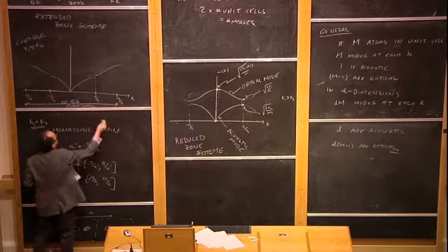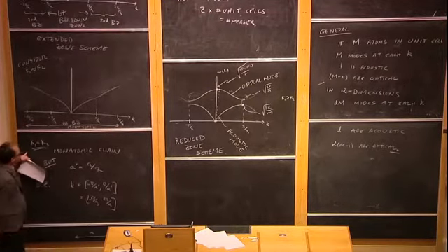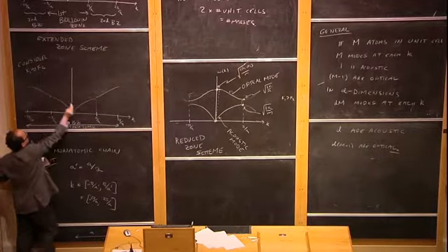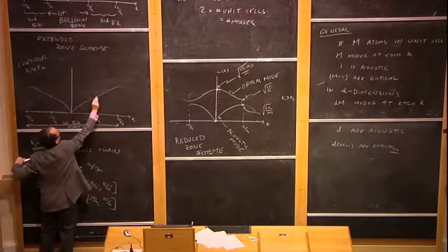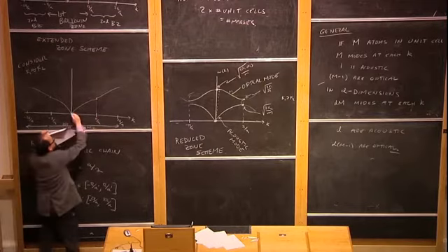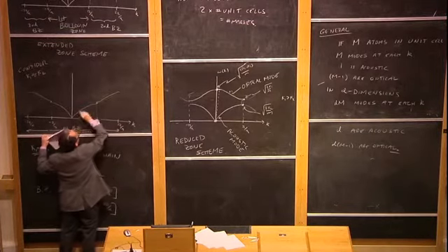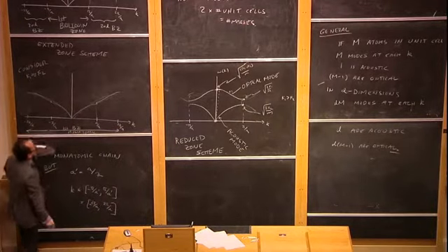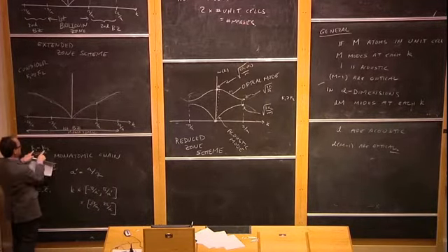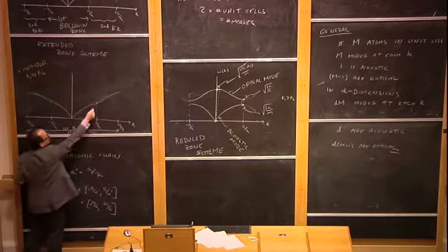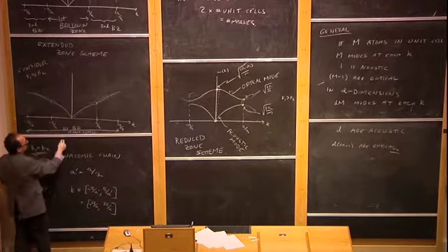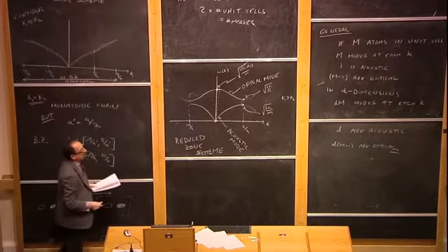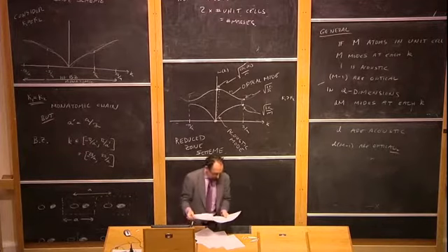Monatomic chain. And then if you make kappa 1 and kappa 2 slightly unequal, you open a small gap at the new Brillouin zone boundaries at pi over a. Okay? But really, what's underlying is a single mode for the monatomic chain from here to here and here to here, just a single connected mode, and when you make kappa 1 and kappa 2 slightly different, you open up a small gap at the Brillouin zone boundary, with the new smaller Brillouin zone associated with the new larger unit cell. Okay?